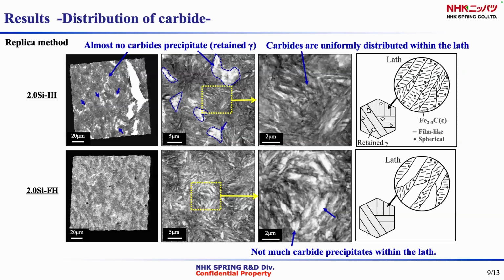We also observed the distribution of carbides for 2.0Si-IH and FH steel with the replica method. In 2.0Si-IH steel, there were some white areas where the carbides did not precipitate much. This is thought to be retained austenite. On the other hand, in the areas except the retained austenite, many carbides appear to be uniformly distributed within the grains. In 2.0Si-FH steel, there was less retained austenite, but the lath shape can be seen clearly. In other words, there are many laths where the carbides did not precipitate much.